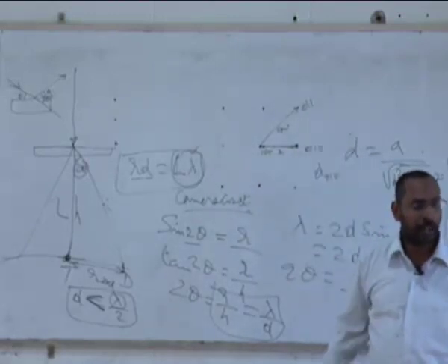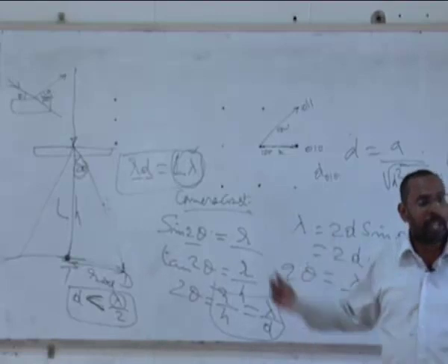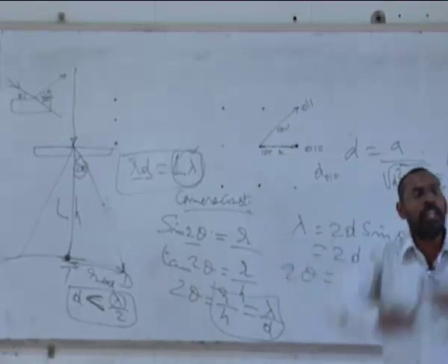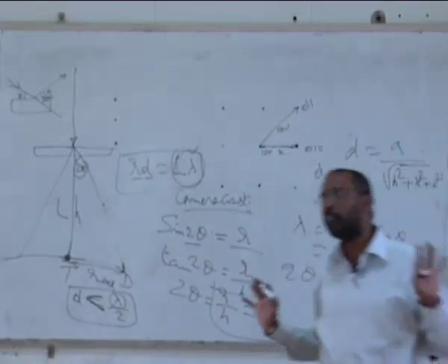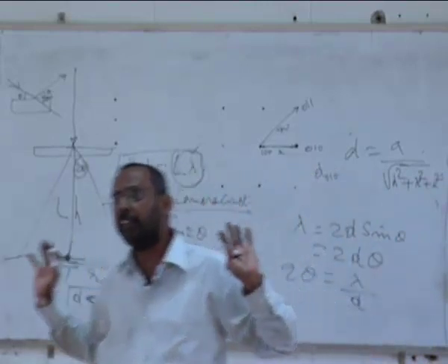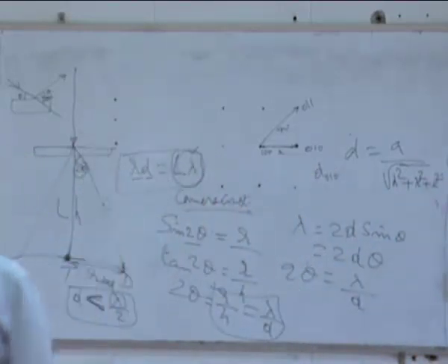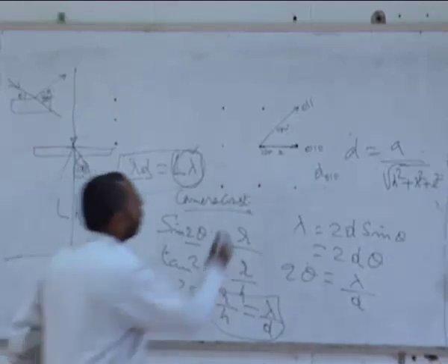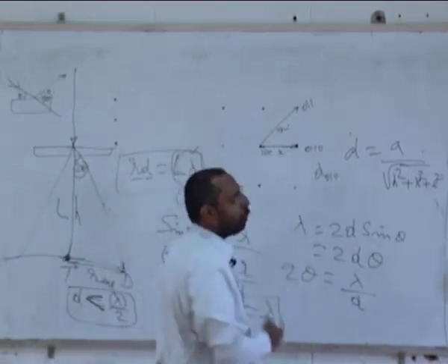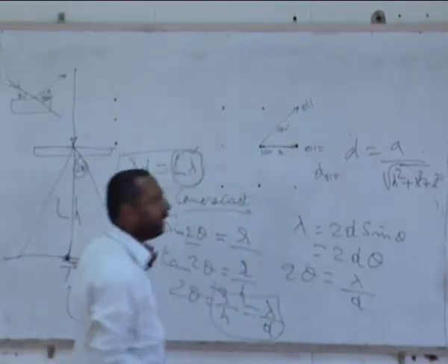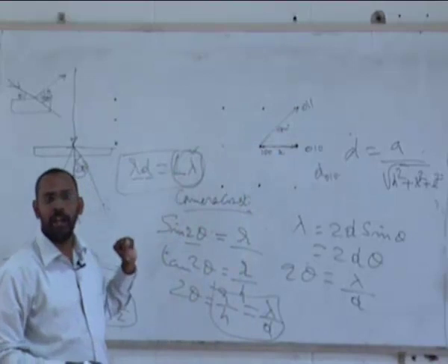Right? I have already indexed it, because this step of calculating comes only after my indexing the diffraction pattern. I have already finished indexing the diffraction pattern. I know each spot, what is the HKL of that. Once I already know the HKL of each spot, I just need to measure the distances between the transmitted spot and the diffracted spot. Once I measure this R, I calculate from that R what is the D using this formula.